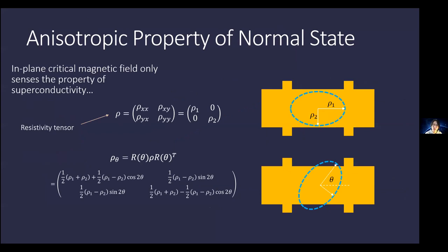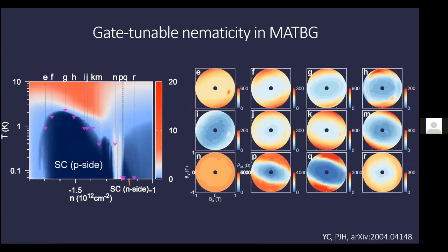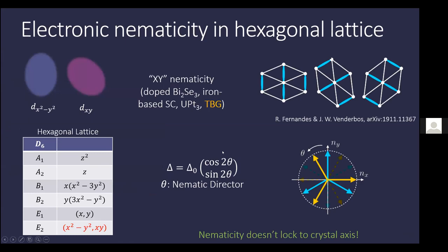Regarding the question of what determines the angle of the anisotropy, I think it is basically a combination of the intrinsic nematicity and some small strain inside the system. If you thermocycle the system, the nematicity direction is always the same. But in different samples, it can be different. There is also one uncertainty in this system, which is that we can't really know the crystallographic axis of the twisted graphene. So comparing from sample to sample is kind of tricky. Okay, I see.